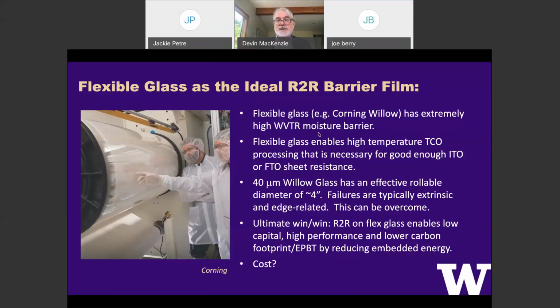But it also is really important because it enables high temperature transparent conductors. We take for granted when we do our spin coated samples on our little chips, we get our little FTO or ITO, and it's like 10, 20 ohms per square. That requires a 300-400 degree C deposition process. You can't do that on plastic substrates. And we'll show you how good or not so good the best ITO on plastic substrates is. So to me, plastic barrier substrates in this space is kind of dead in the water.